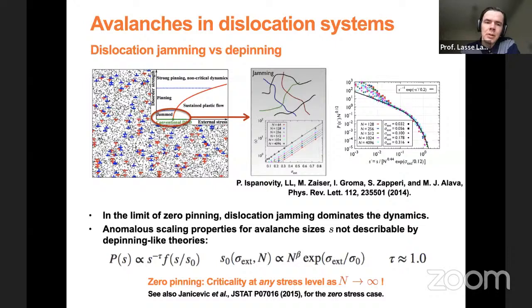So there are, of course, now different regimes of this plasticity here. So one is where you basically only have these dislocations. So you don't have any additional defects in your crystal, only dislocations moving around and forming maybe some structure, but no other defects to interact with for the dislocations. So in this case, what we have is something we call dislocation jamming. So the dislocations form these structures due to some self-induced constraints for the motion. And that's why eventually, if you just keep the stress constant at a small value, the dynamics will eventually stop.